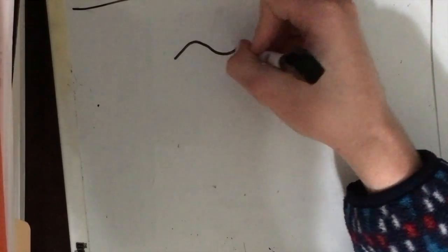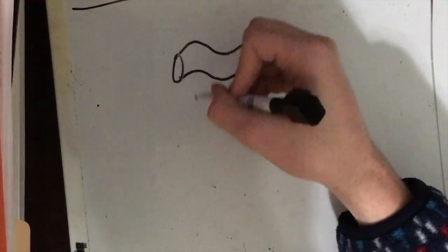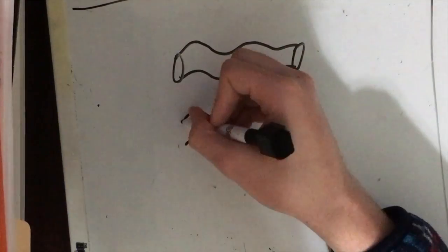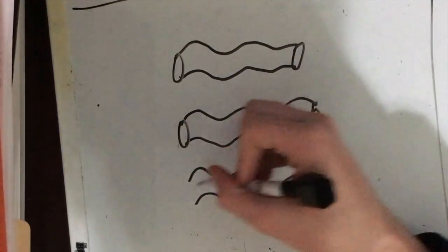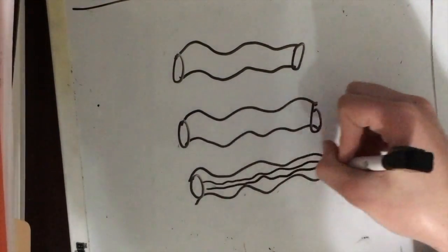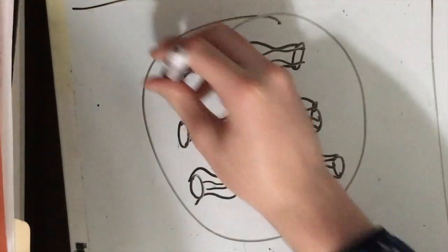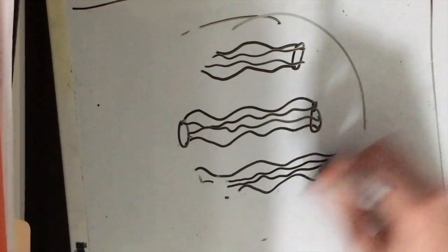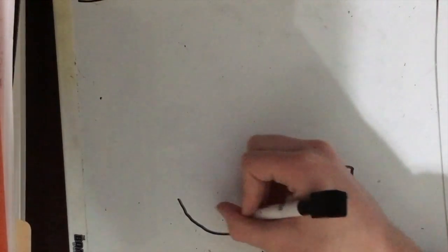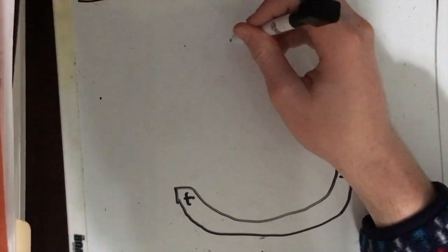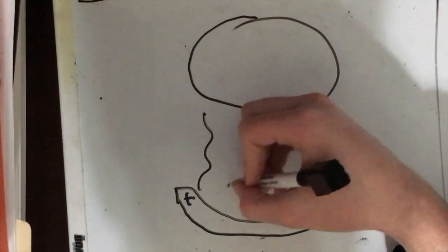Now, let's get into some flux pinning. According to the Meissner effect, the superconductor will tend to expel all magnetic fields inside of it. Type 2 superconductors have extremely thin magnetic fields penetrating them. These are called flux tubes. Inside each of the magnetic flux tubes, superconductivity is destroyed, causing the superconductor to keep the magnetic tubes pinned in the weak areas. In this state, if you move the superconductor, the flux tubes will move, causing the superconductor to be trapped in mid-air, which leads to the floating appearance.